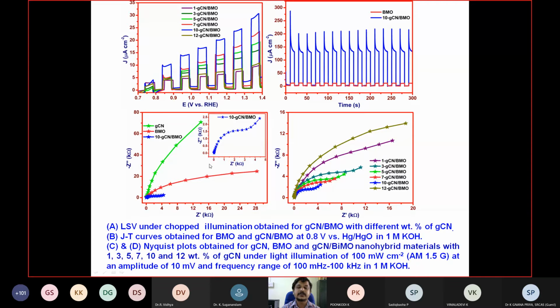And the charge transfer dynamics, we also investigated using impedance spectroscopy. Here you can see the control material shows a large semicircle, but the best material shows a small semicircle. That implies very low charge transfer resistance for this material. So when compared with the other materials, that's why this material shows excellent performance.